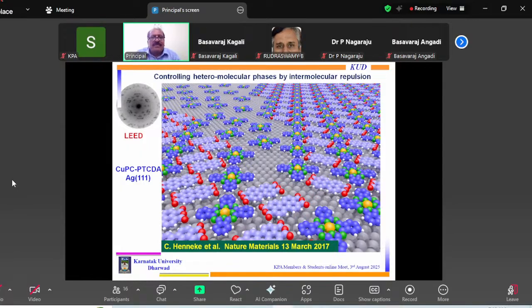This is again a very interesting picture, of course computed, but it has been recorded also. It is a copper phthalocyanine and one other organic molecule together deposited on a silver 111 surface. You can see the beautiful pattern, just like tiles. In fact, that is how we can do atomic level science in material science, particularly monolayer formation. We can deposit the materials that we want so that we can create more and more functional materials. And here is the electron diffraction pattern of such monolayers created.